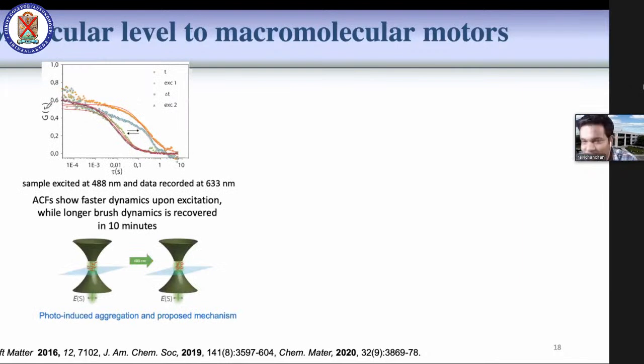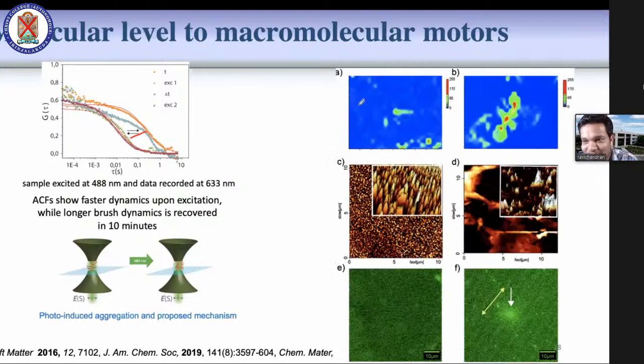So here I showed two dynamics observed, the short dynamics and the long dynamics. The short dynamics are coming from the side chain of the azobenzene, and the long dynamics are coming from the main chain of the polymer brushes, which is cyanine 5, which reads the information. And this process is reversible. It happens in a few seconds, going from long to short dynamics, but it reverts back after 10 minutes. So it can be confirmed by using Raman and AFM.